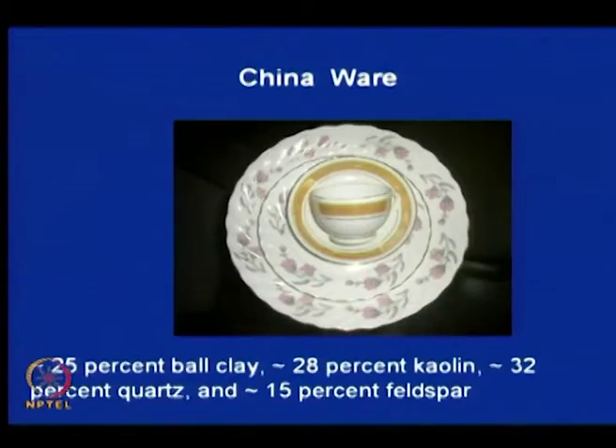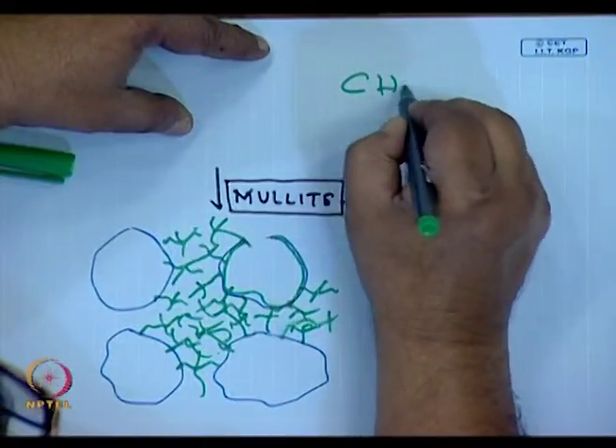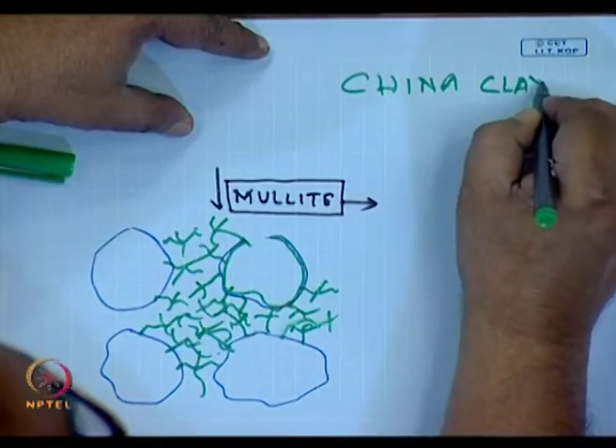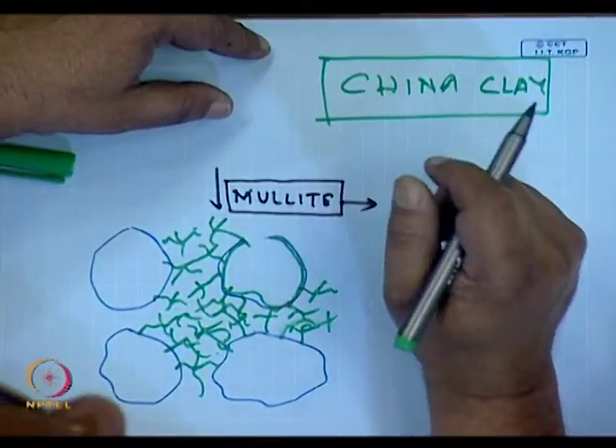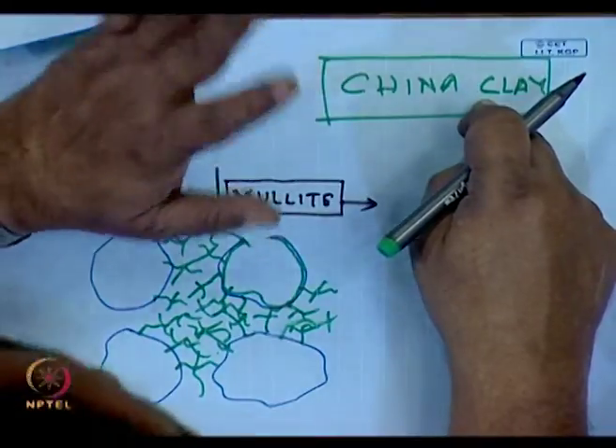This is of course done by having purer and purer clay. The 400 rupee cup would be using what we call China clay, a very, very white clay, almost like kaolin. It would be very free of impurities, and as a result, the 400 rupee cup is much stronger. It is also thinner, whereas the 2 rupee cup is definitely thick. In this ceramic fabrication and processing course, we will look at such events as how to control sintering and microstructure, so that we can get very good products.